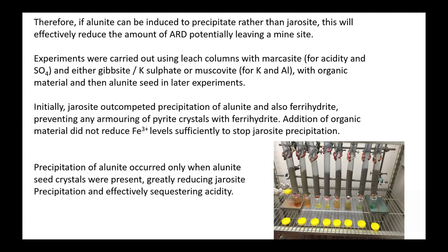However, seeding had worked for magnetite, it had worked for sulfides. So we added some alunite seed, or rather Farah added it. And when she added alunite seed, it worked really quite well. And she was able to get alunite to precipitate, and it could outcompete jarosite for the potassium in solution and effectively stop the jarosite precipitating and precipitate a mineral that's likely to remove some acidity on a fairly long-term basis.